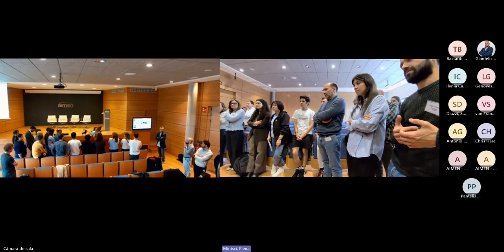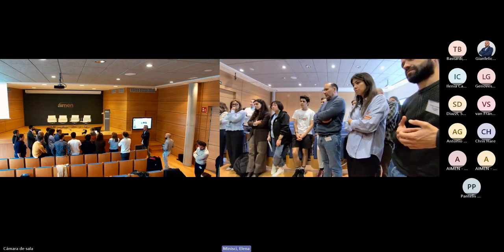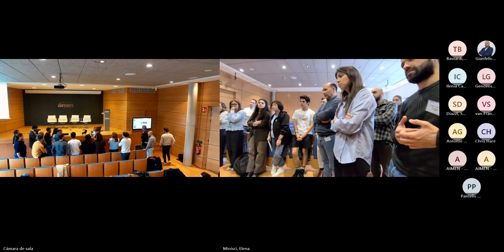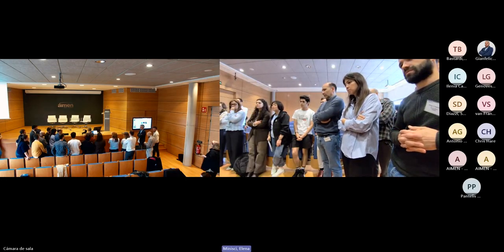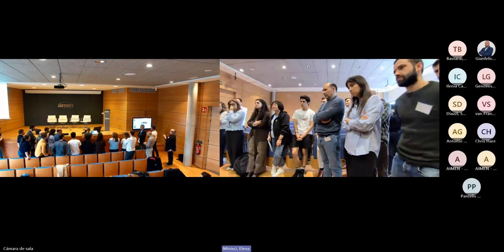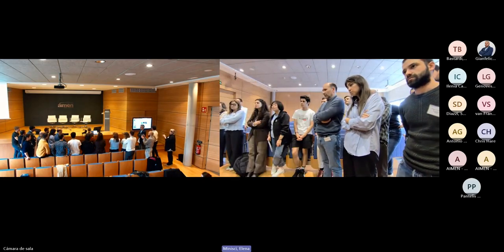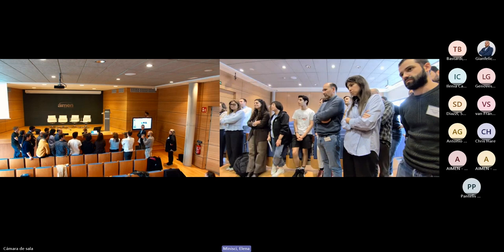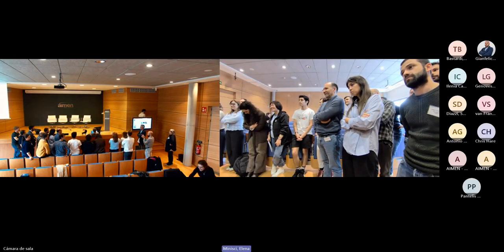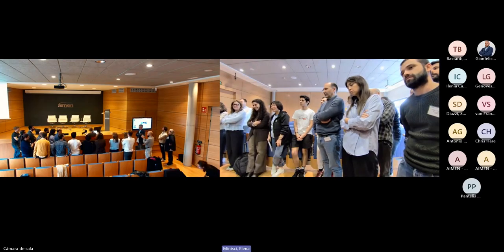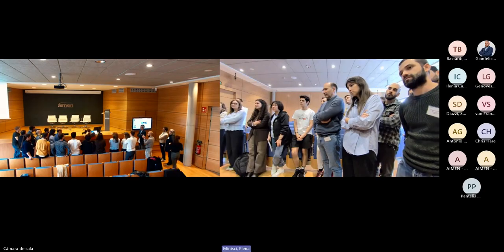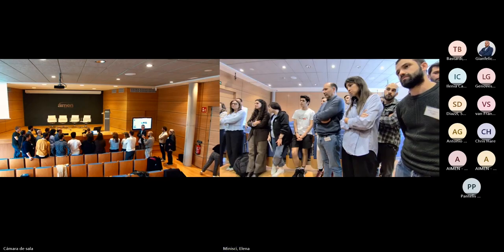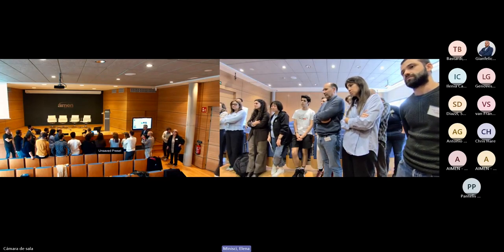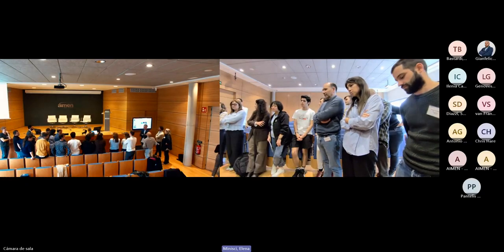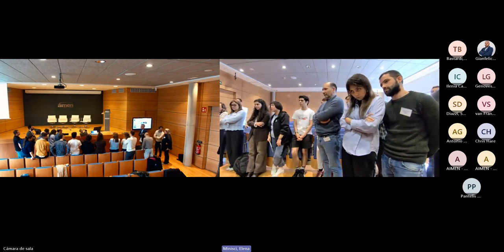We have here this terahertz sensor where we put a sample. We need some reflective foil behind it. It's not perfect because there's some air between. But you can see the reflection and you can see my finger. It's highly absorbing water. Okay. Does it work better? Yeah. And the terahertz source is here and illuminates the sample. And now it's dry, so in the reflection we don't have any absorption in the measurement.